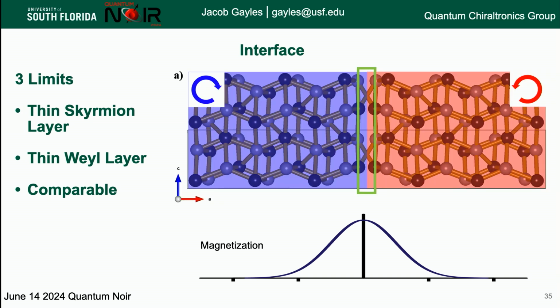We have 3 limits to look at here. We'll only talk about one today, just to save time. So there's 3 limits where one case is where we have a very thin skyrmion layer, and that's what happens here. You have a very thin skyrmion layer and then very large Weyl materials on either side. And the other case you can look at, of course, is where you have a very thin Weyl layer. That's where you get this gap opening, get this quantum anomalous Hall effect. And you also have these cases where they're comparable.